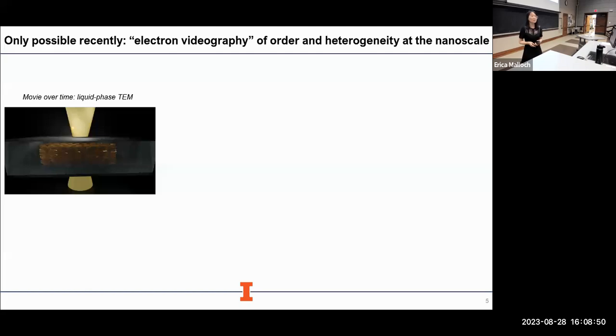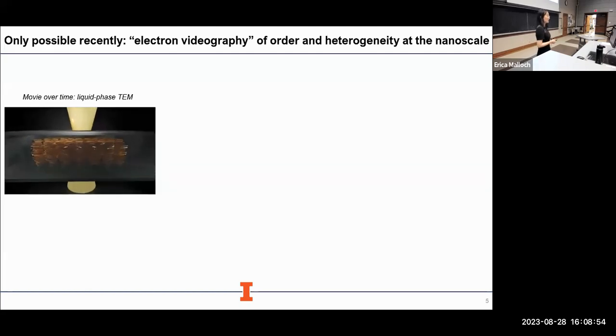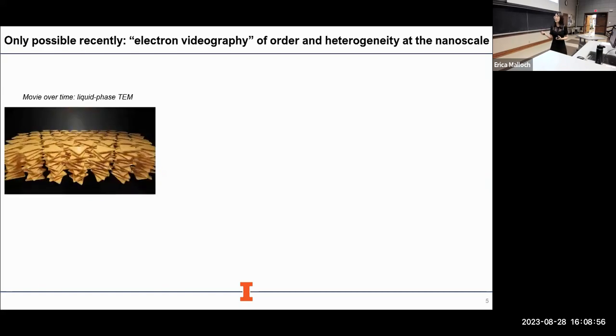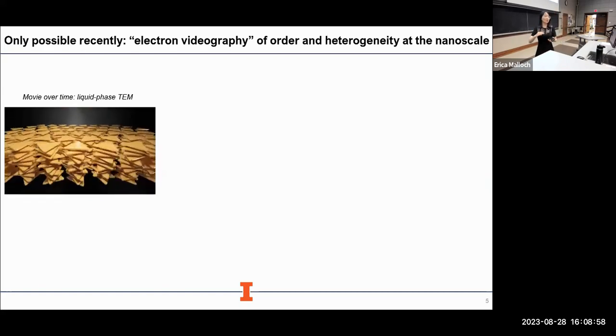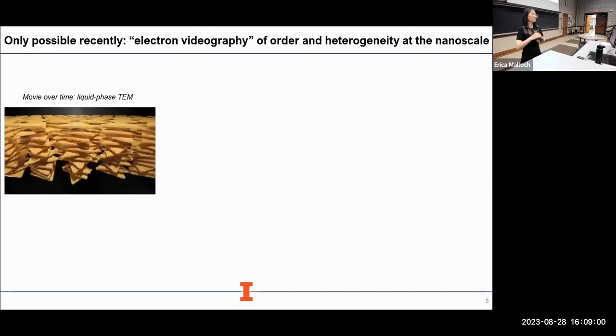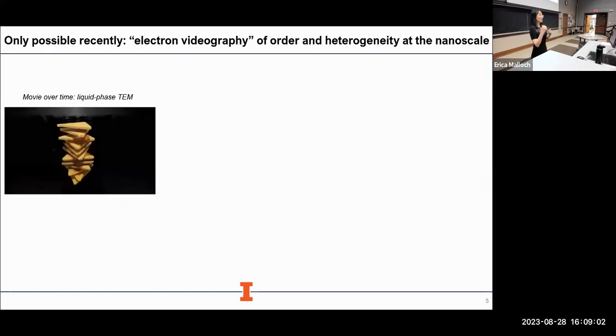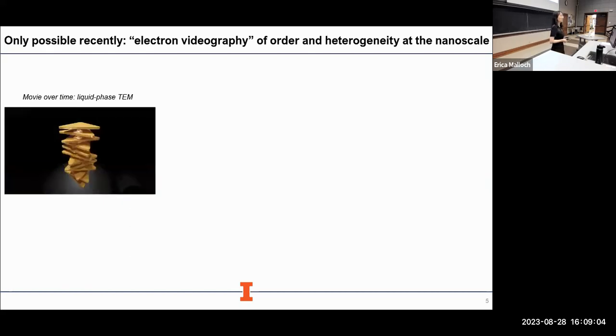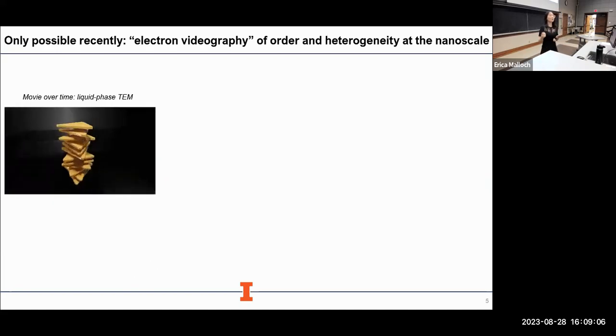Instead, we can actually take movies. And we have 3 different ways to take movies. The first is liquid phase TEM, shown here, which allows you to use 2 membranes to seal and sandwich a liquid sample and then put it into the high vacuum TEM. So by doing so, not only can you resolve the nanoscale structure, you can also visualize the vivid thermally agitating motions in the presence of solvent molecules.